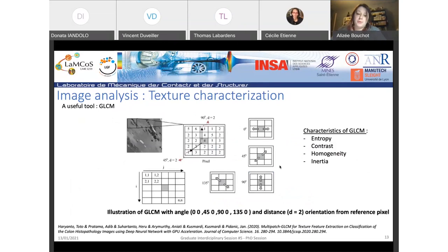We have here an illustration of this function, of how it works. The GLCM will count the number of times a pair of pixels, in terms of shade of gray, is found in the image for a given distance and angle. For example, here, the distance is 2 and the angle is 90 degrees. We count the number of times we see the pair 4 and 1 in this direction, and it's tabulated in this matrix, the co-occurrence matrix.